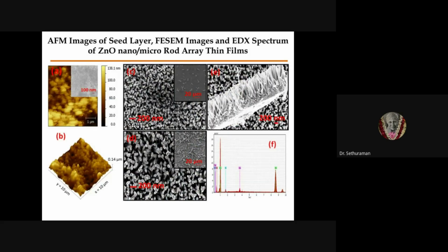From this work, we see beautifully distributed zinc oxide nanorods, and on the surface of the nanorods we found some micro rod assembly also. You see the black portion is completely nanorod assembly, and on top of the perpendicular nanorods we found zinc oxide micro rods also, lying on the surface of the nanorods. So this is a uniformly distributed micro rod assembly on the surface of the zinc oxide nanorods. Here also we have used a seed layer concept.